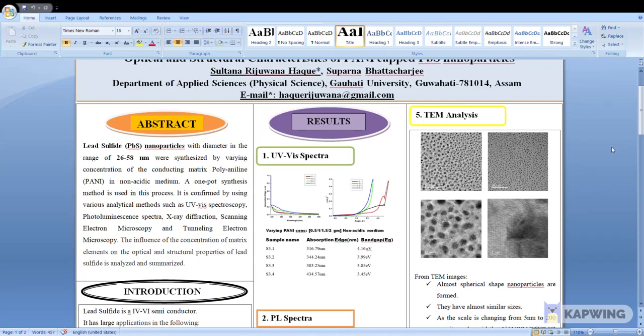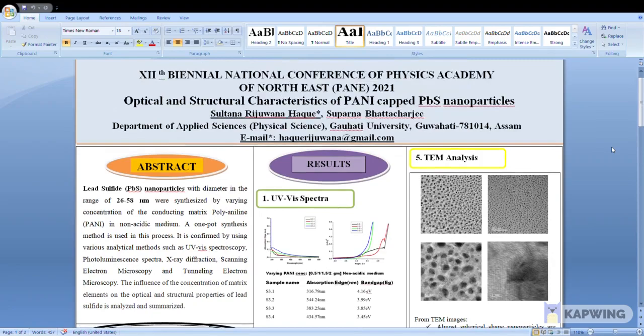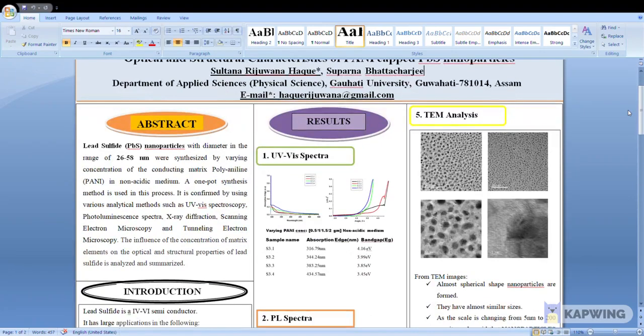The topic of my poster presentation is optical and structural characteristics of PANI-capped lead sulfide nanoparticles. In this paper, we have synthesized lead sulfide nanoparticles with diameter in the range from 26 nanometer to 58 nanometer by changing the concentration of conducting matrix polyaniline in a non-acidic medium. A one-pot synthesis method is taken in this process.